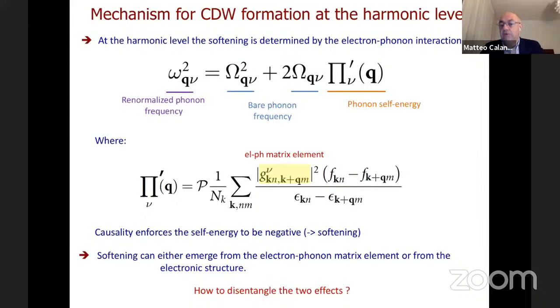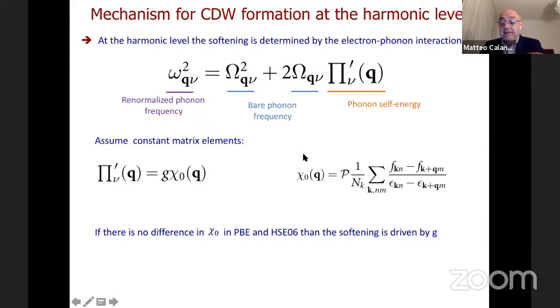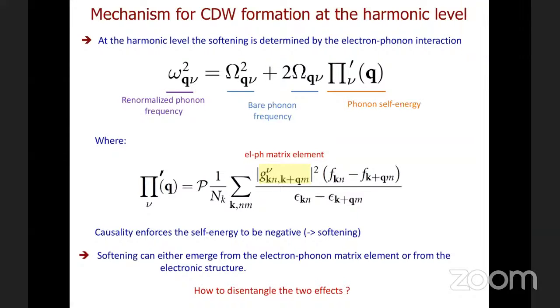The denominator is not becoming smaller. What drives the transition is the matrix element. The matrix element is how the Hamiltonian felt by the electron changes when you displace an atom. So the k and q dependence of this matrix element, and the dependence of the matrix element on the electron-electron interaction, is what gives you more softening than the standard anomaly theory. So this is the standard anomaly theory with no matrix element, and this is a bit more complicated anomaly theory at the harmonic level. Indeed, depending on the approximation of the electron-electron interaction, the gap changes. So different degrees of electron-electron interaction renormalize the electron-phonon matrix element differently. I see.